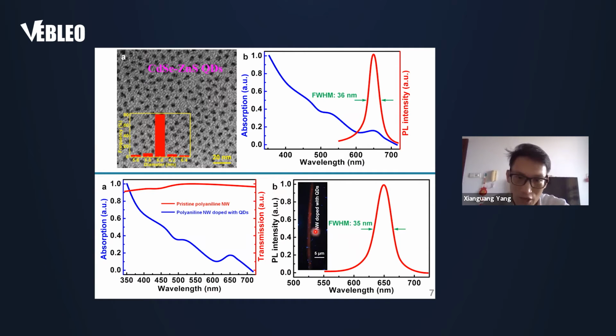Figure B shows the emission properties. This is the PL spectrum of the polymer nanowire doped with quantum dots. The inset shows the polymer nanowire excited by incident blue light. You can see this scattered blue spot is the incident light scattering, and the quantum dots embedded in the polymer nanowire were efficiently excited and emitting red light.